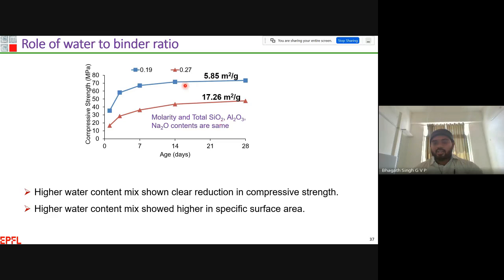And why is it happening in these two mixes? Because in these two mixes I have maintained the molarity, total reactive oxide ratios, and the contents, and everything is the same. The only variable is the water to binder ratio. Then I determined the specific surface area of these two materials at 28 days. The 0.19 water to binder ratio mix has a lower specific surface area, whereas with 0.27 the specific surface area is about 17.26 square meters per gram. Due to that, the specific surface area also clearly plays a major role in strength development, but we should not use a higher water to binder ratio if we want to achieve higher compressive strength in our fly ash based binder. Still, we are working on this particular component currently.